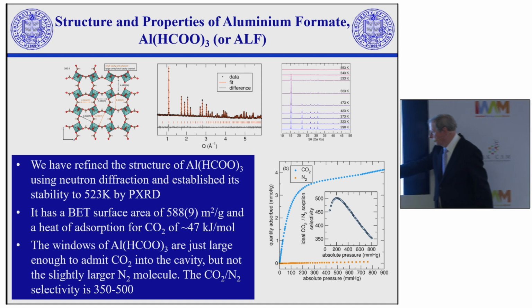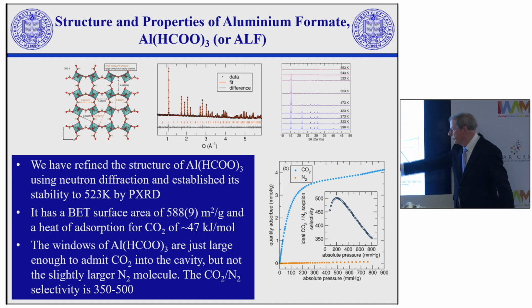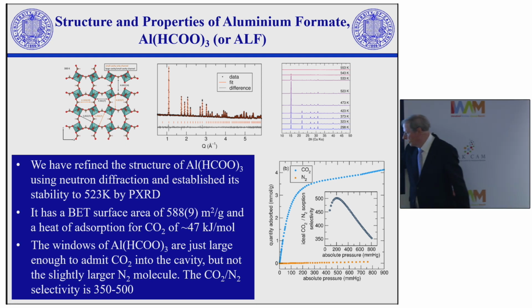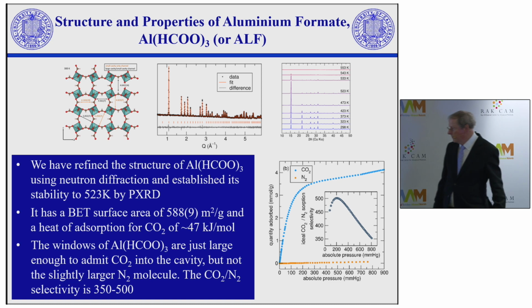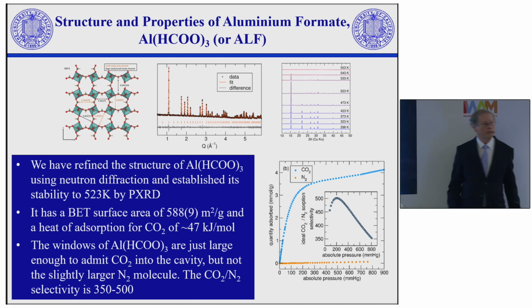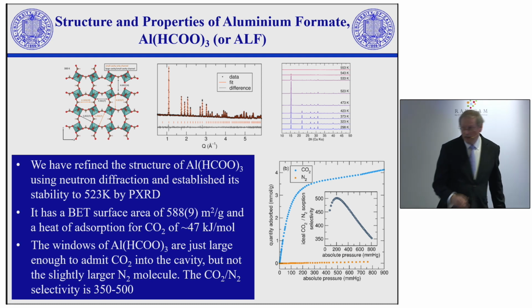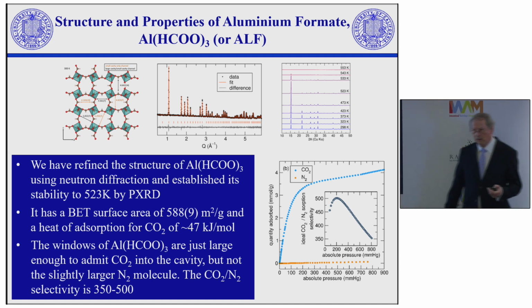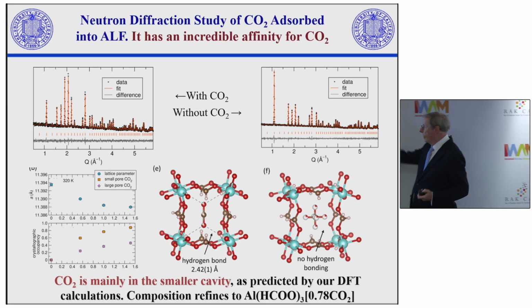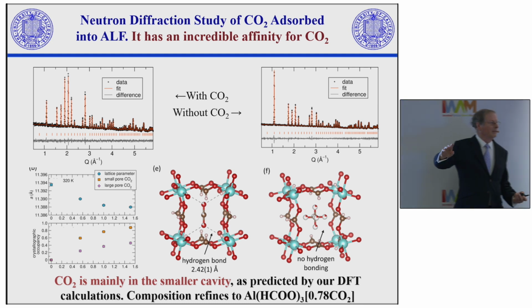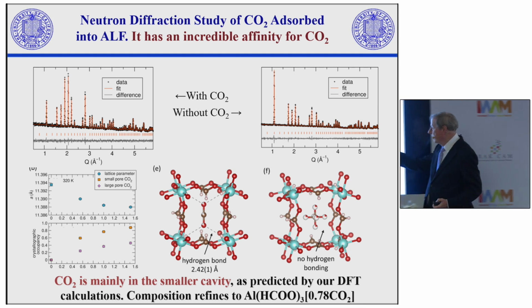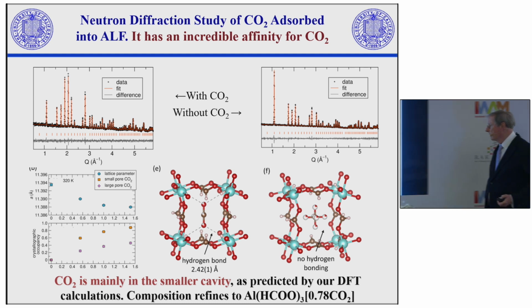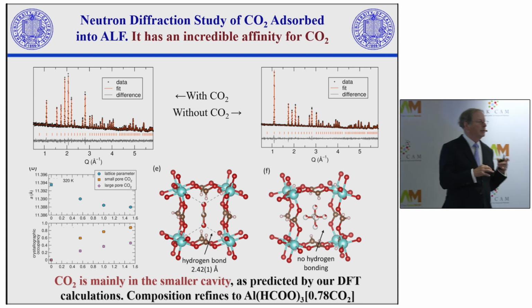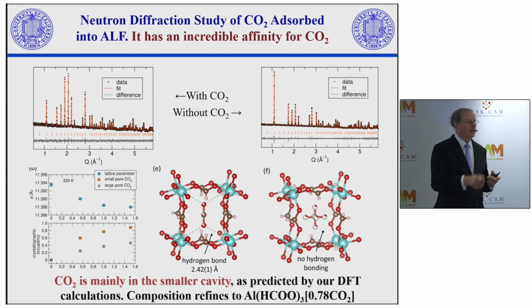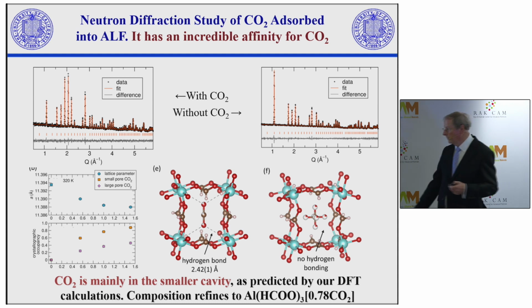But this is the adsorption of carbon dioxide. This is at room temperature here. That's in blue. And that's the adsorption of nitrogen in brown at the bottom. So you get a selectivity of CO2 over nitrogen of several hundredfold. And so this is a magical system. We've looked at the structure of it using that technique that we'd worked on like 50 years ago, that Rietveld method, and we've looked at it with and without carbon dioxide in the channels. And this material has a fantastic affinity for carbon dioxide. Carbon dioxide is basically like a hand in a perfectly fitting glove. And so it loves carbon dioxide.